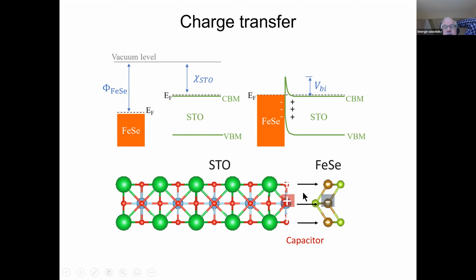This means you get a dipole layer shown at the bottom here, the plus and the minus signs. Okay, so the STO is going to be positively charged, probably accumulated at the surface, and the iron selenide will have a negative charge. And when you do that, you have a kind of capacitor. They, of course, attract each other. And indeed, in density functional theory, you find that now the distance between the iron selenide and the STO gets smaller. But there will be an equilibrium where the amount of charge transfer simply is stabilized. And that turns out to be this magic number of 0.12, I think it is, per iron.